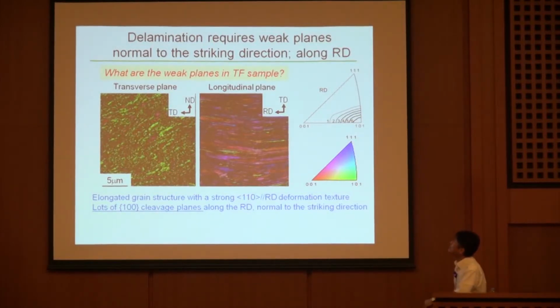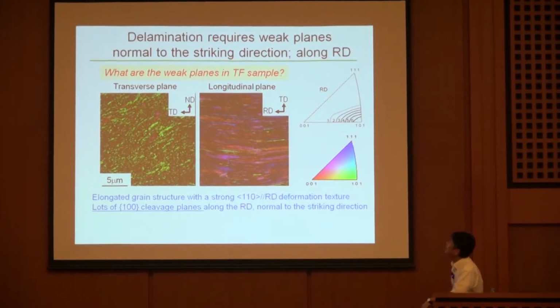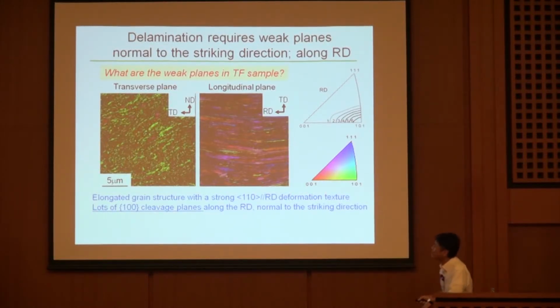So delamination requires weak planes normal to the striking direction, RD. So what are the weak planes in the TF sample? This is the microstructure for the transverse plane and the longitudinal plane with the orientation mapping in different colors. When you look at this strong 110 RD deformation texture, there are lots of 100 cleavage planes along the RD, that is, normal to the striking direction. The 100 is the weak plane in BCC steel, so it would be the plane for delamination.